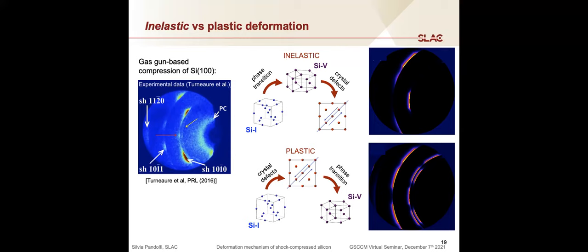The difference between inelastic and plastic is that what was termed inelastic deformation is a deformation mechanism for which we first have a state of uniaxial elastic compression. In this case, only one of the axes is being compressed and the others are kind of unperturbed. So we do have shear stress because of the imbalance between the direction that is being compressed and the plane perpendicular to the shock propagation. After a certain threshold, the system starts relaxing toward a hydrostatic state of compression.